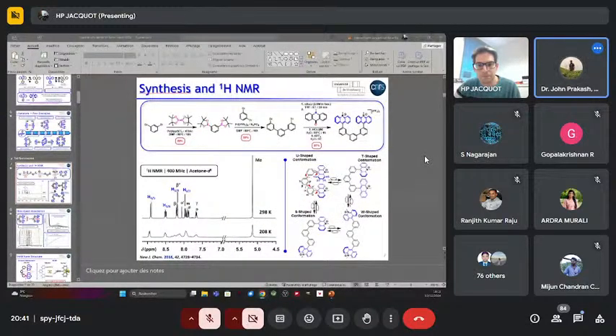The question is simple. Is there any possibility of polymer formation or polymer product formation? I'm not sure I understand. I mean, maybe in this case, for the second step, sir, am I right? Yes, sir. So actually, what we do is that we use a huge excess of the dibromo derivative, which is pretty cheap. So we never observed the polymers. Often, what we do see is that we have an extra phenyl ring. That's a very good question, because usually what you can do is form the macrocycle, basically 2 of those. But in our case, we cheat on the conditions, so we use 5 equivalents.